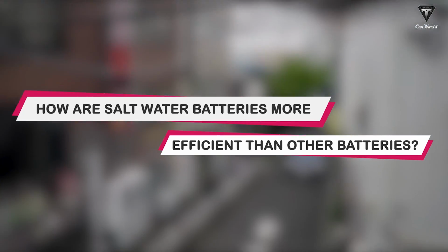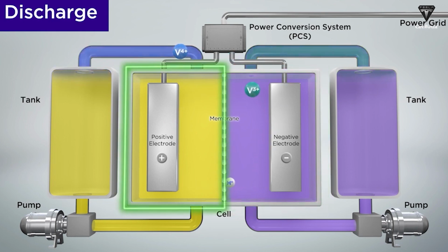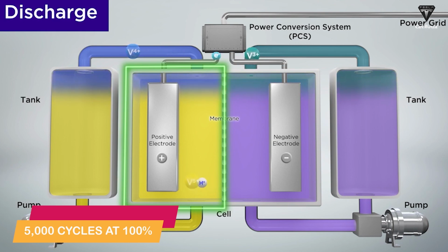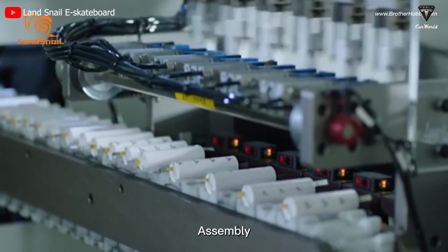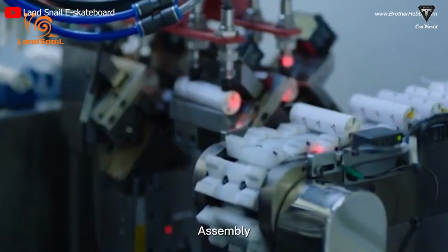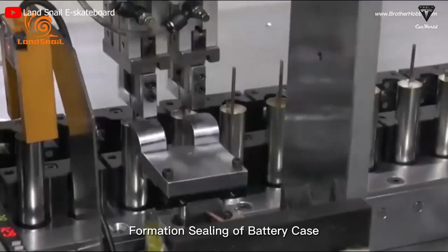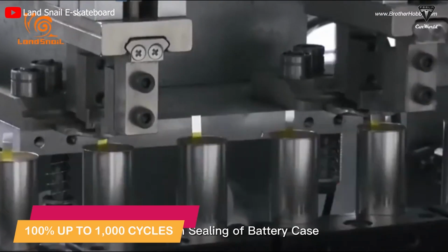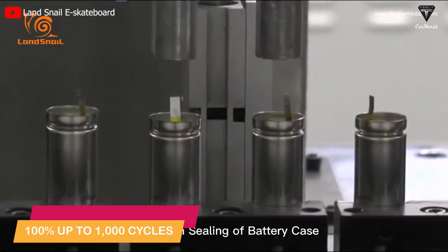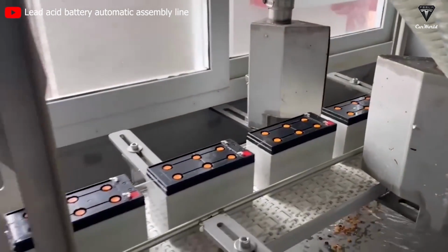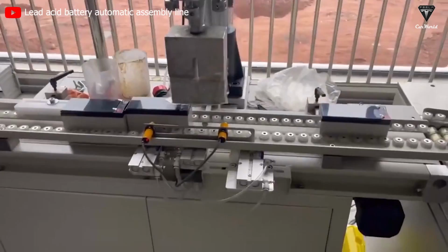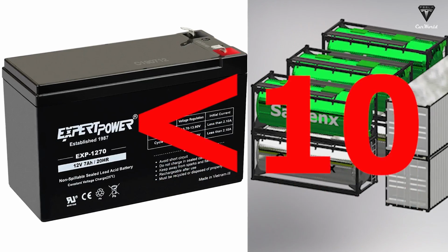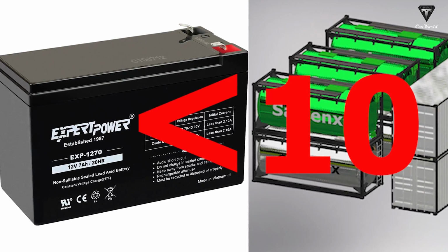Next, how are saltwater batteries more efficient than other batteries? With a life cycle of roughly 5,000 cycles at 100% depth of discharge, saltwater batteries have a significantly higher life cycle compared to lithium-ion batteries, which have a conventional life cycle of 100% up to 1,000 cycles. Additionally, lead-acid batteries will gradually lose capacity after only 500 cycles, which is 10 times less compared to saltwater batteries.